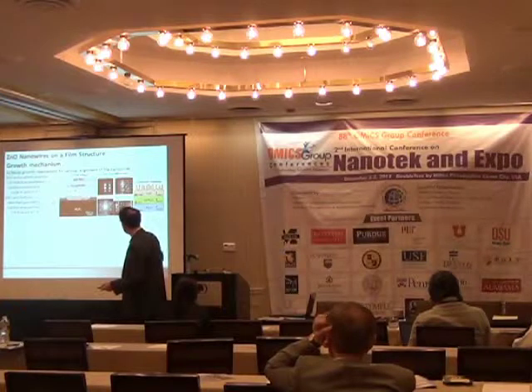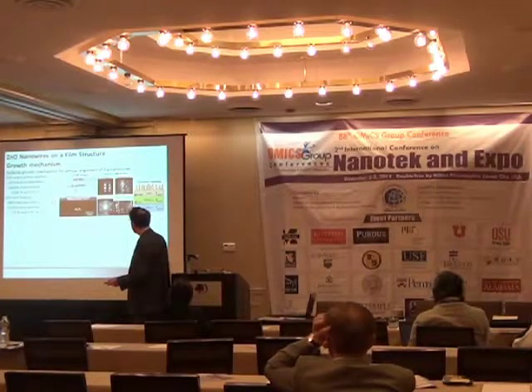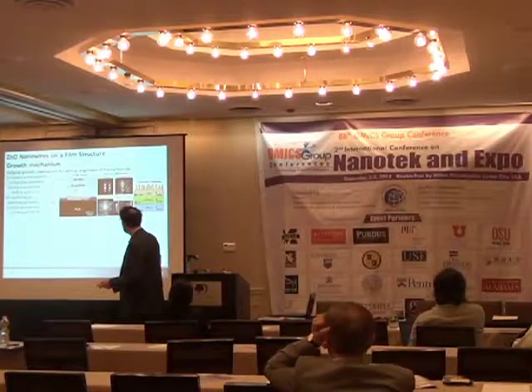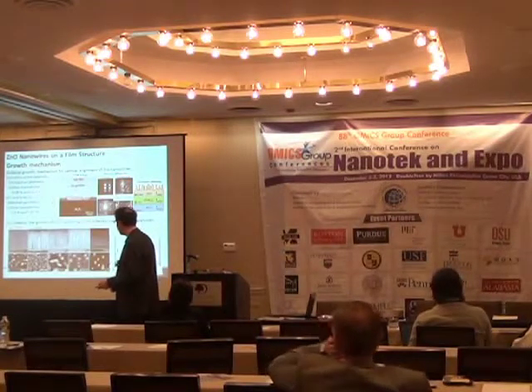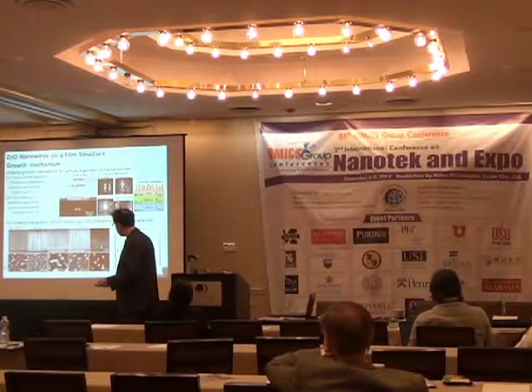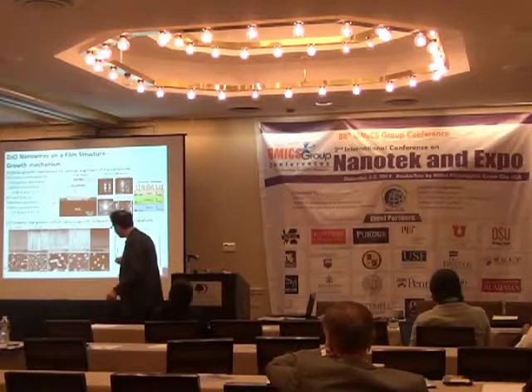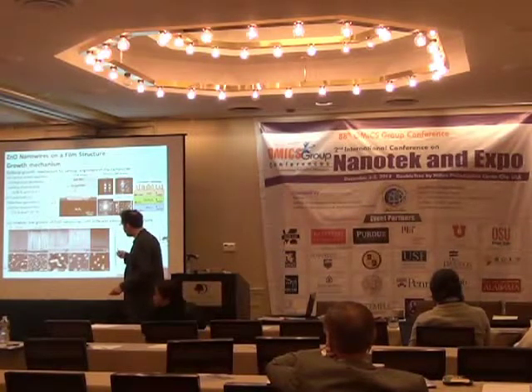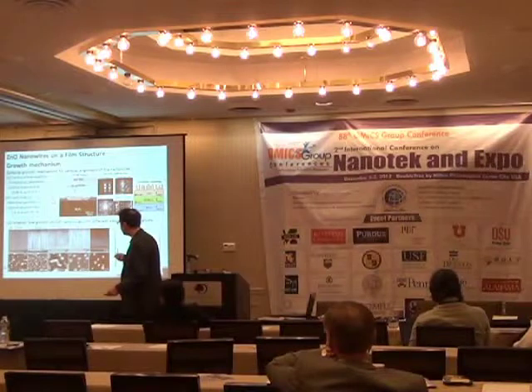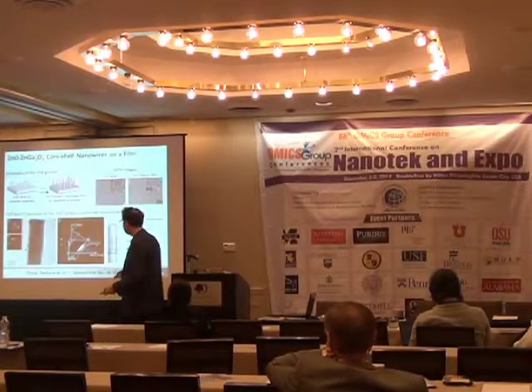And at the end, what we have is the sapphire, spinel interlayer, and the zinc oxide nanowire on film structure in a single crystal form. So this is the schematic of the material that we have fabricated. We can control the thickness of the underlayer of zinc oxide, and the height of the nanowire, by changing the amount of gold that we use.